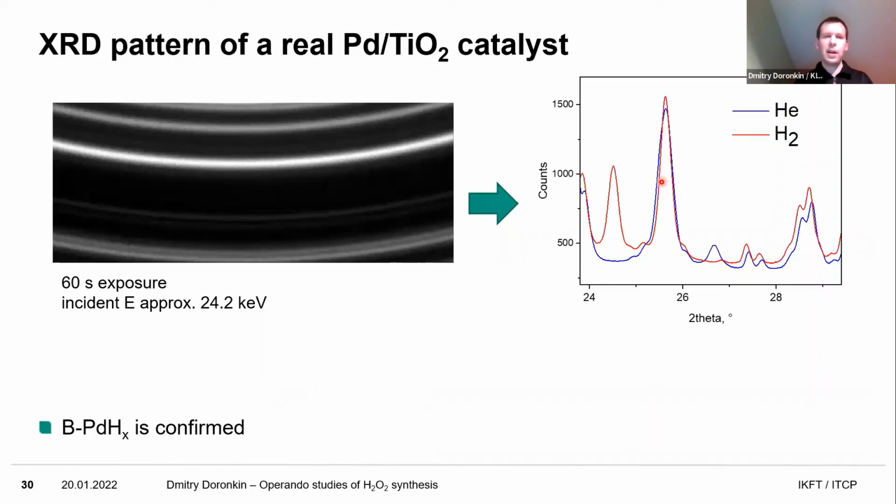So first, I'm showing the X-ray diffraction patterns. Since we are not dealing with a model catalyst with just palladium nanoparticles, but a mixture of different polymorphs of titanium dioxide as a support, so it's the industrially relevant P25 support, we had to make efforts to find the reflections which we can use to identify hydrides and